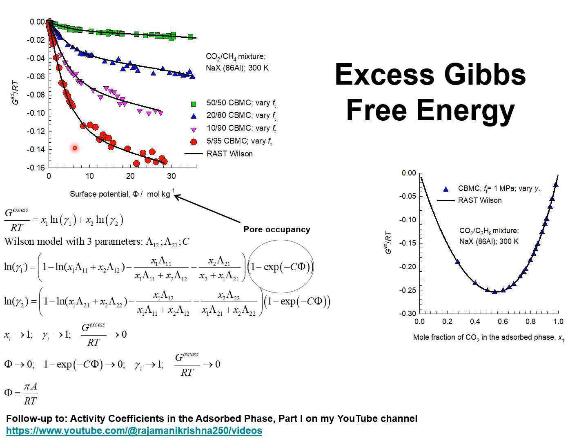I had used this graph to demonstrate that the excess Gibbs free energy divided by RT is a function not only of the mole fraction in the adsorbed phase, but also of the surface potential. That is a proxy for the pore occupancy.